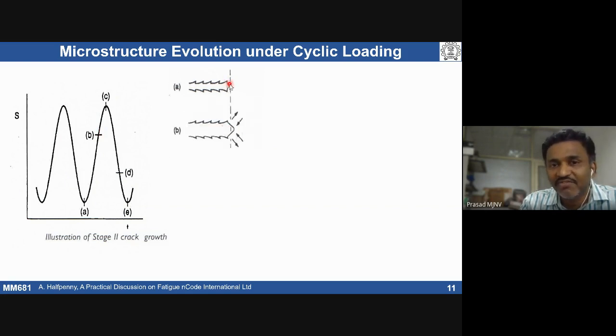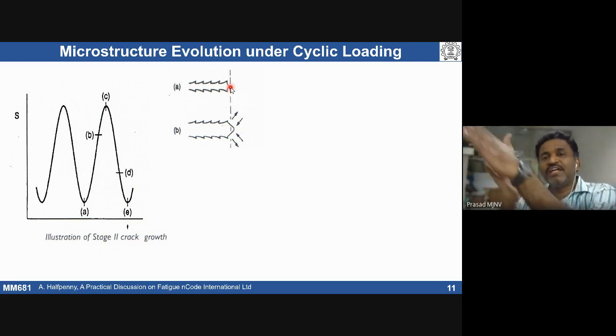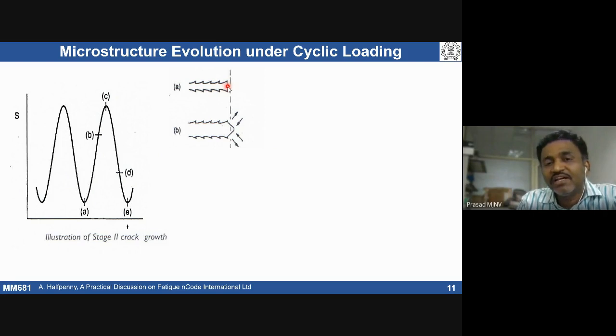When I apply stress from A to B, what happens? The crack front is going to be sheared, pulled. There will be some shearing activity in front of the crack tip, so the crack front is going to move because of plastic deformation. We are applying some stress, so there is shearing activity. Around the tip the stress will be very high, which leads to plastic deformation. That means shearing activity is taking place, and it is going to pull the material. So this shearing activity can pull the crack front.